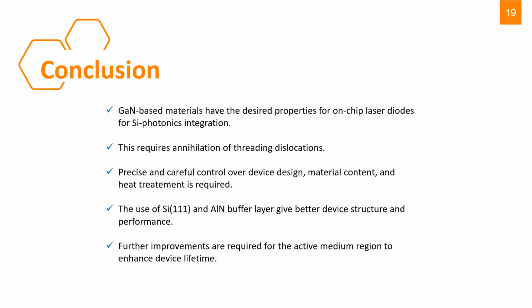So as a conclusion, we could say that gallium nitride materials are desired for on-chip laser diodes for silicon photonic integration, but this requires good control of the device fabrication, device design, material content, and also heat treatment in order to annihilate or at least reduce as much as possible the threading dislocation density in the device, and hence increase the quantum efficiency and light extraction efficiency of the device. Studies showed that the use of silicon 111 substrate and aluminum nitride buffer layer are good solutions for better device structure and performance, and also further improvements are required for the active medium in order to enhance the device lifetime and limit the degradation of the device.